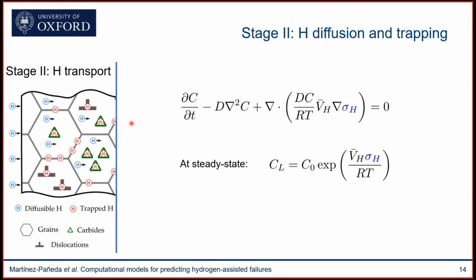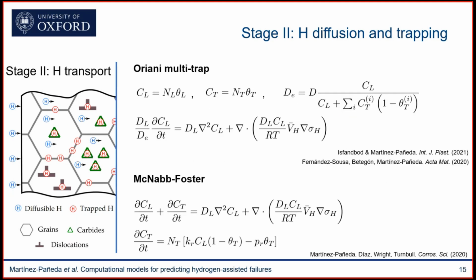But anyway, this is the transport of hydrogen. So by solving this equation, you can predict the distribution of hydrogen within your component. But this is only one part of the picture. We know that hydrogen not only diffuses freely through the crystal lattice, it's also sequestered at microstructural features such as traps or defects. So we have developed more generalized extended formulations that can account for these multiple trapping conditions based on either Oriani's equilibrium or McNabb-Foster kinetics.